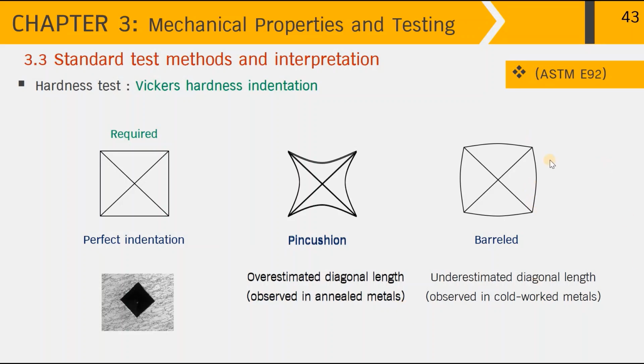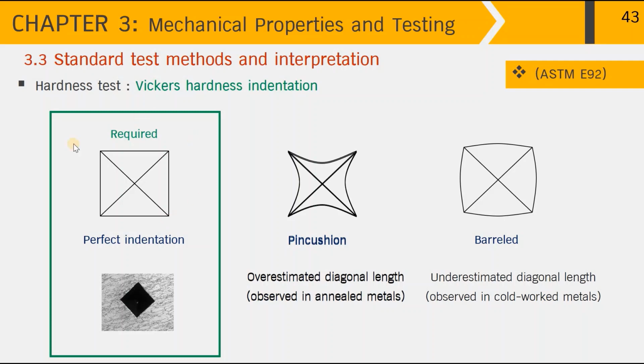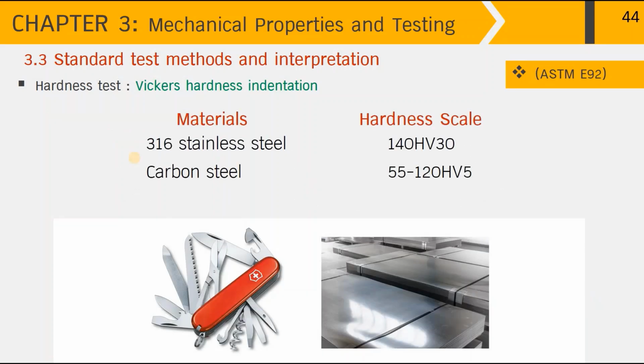On your right here, if the indentation has the barreled shape like this, crossing here are the diagonals that we have to measure. And you can see that the diagonal lengths are underestimated. And this means you will get hardness values that are higher than they should be. And this result may be observed in cold worked metals that you have to be careful about. So what we need is to obtain the perfect indentation with a square base like this to give an accurate result.